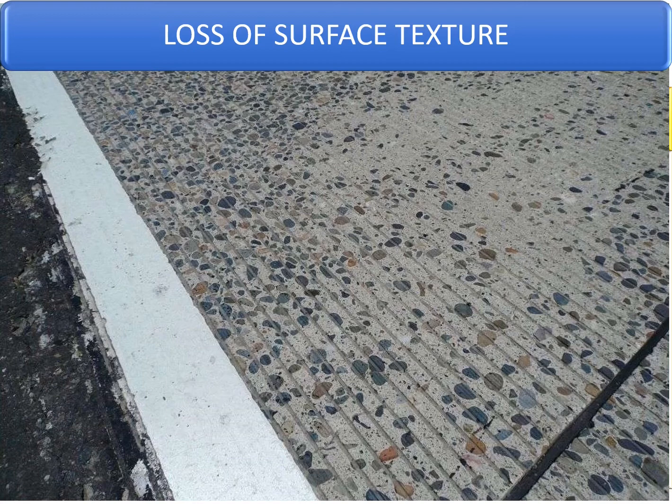Causes include abrasion and polished aggregates, incorrect selection of aggregates, poor construction during the finishing operations, or low strength mortar worn out from the surface due to the traffic. The recommended remedies are transverse grooving using a mechanical method, and surface dressing, that is epoxy based anti-skid surface dressing.